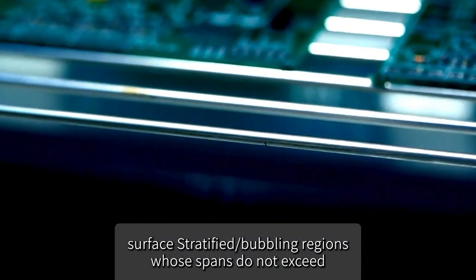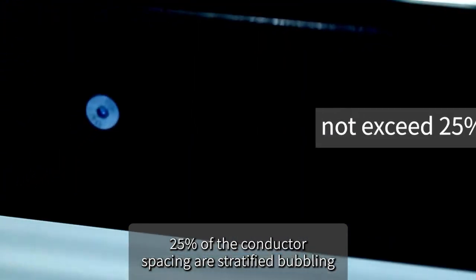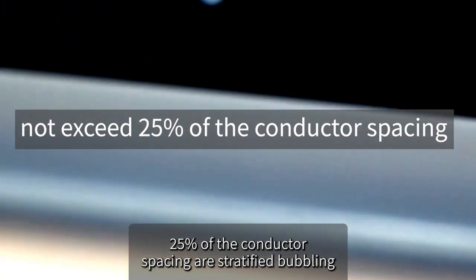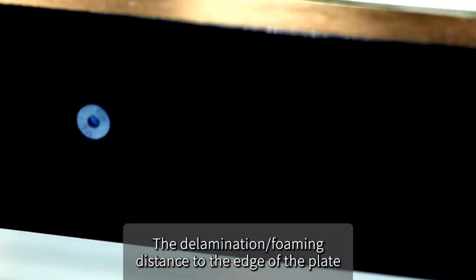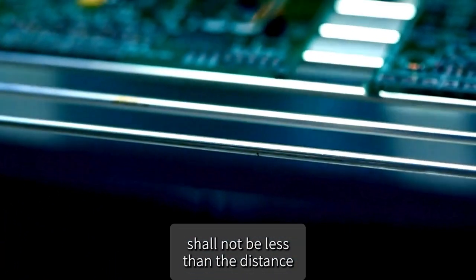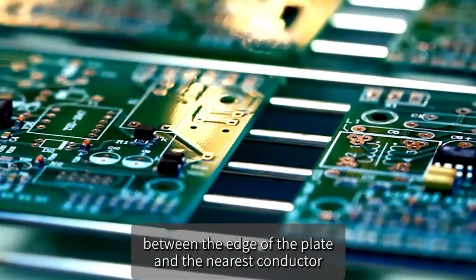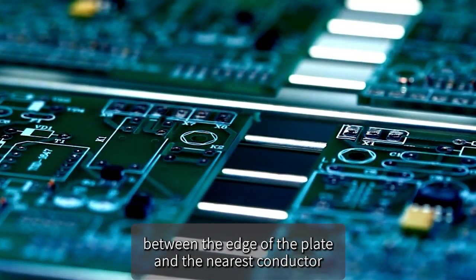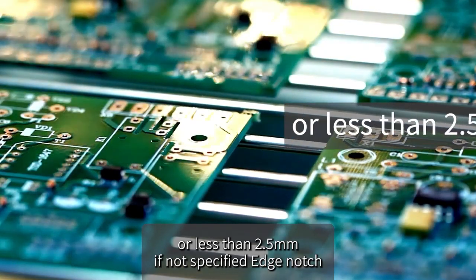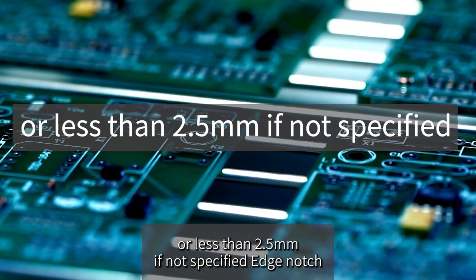Stratified/bubbling regions whose spans do not exceed 25% of the conductor spacing are acceptable. After 3 thermal shock tests, there is no gap on the edge of the plate. The delamination/foaming distance to the edge of the plate shall not be less than the distance between the edge of the plate and the nearest conductor, or less than 2.5 mm if not specified.